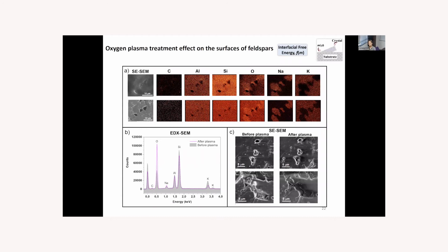Okay, so let me now show you some experiments we've made in order to investigate the effect of oxygen plasma treatment on the surfaces of feldspar. We've done that in order to see if we could pre-activate the particles and the surfaces to facilitate ice formation. So we have characterized the samples before and after the plasma treatment. And you can already see on the EDX maps that the oxygen signal increased in the plasma-treated sample. This is the same cut before and after. Also in EDX, you can see the growth of the oxygen peak is quite big.